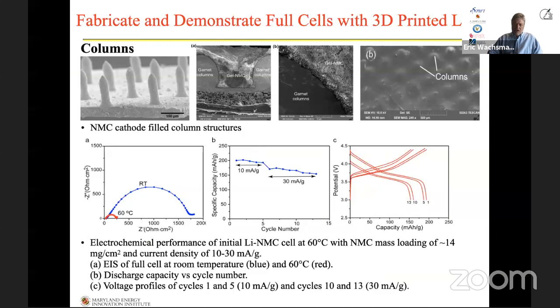The figure to the right of that is then the capacity that we're able to get out of the battery with every cycle. And the data to the far right is actually the current voltage behavior. Each one of those red lines is a charge discharge profile of this all solid state battery, cycling at 1, 5, 10, and 13 cycles at different current densities. And the data in the middle is the capacity that we get out of this on the discharge cycle. That would be the curve going down. That's how much capacity we're able to get out of it per gram of cathode material.